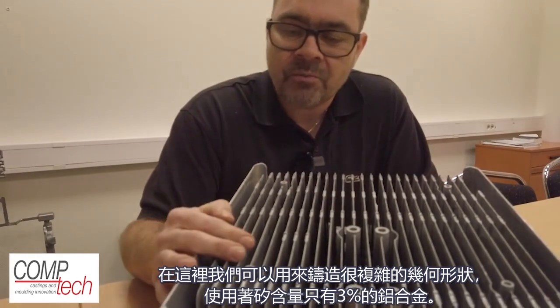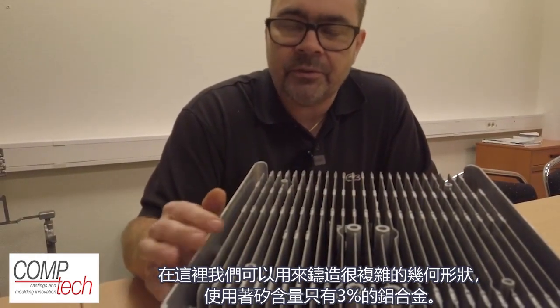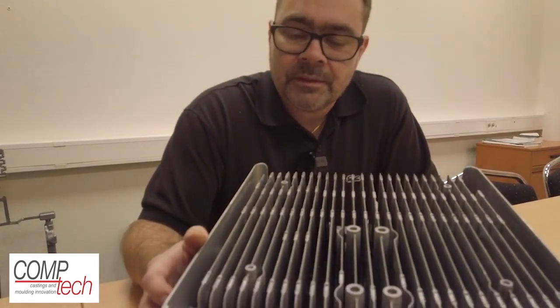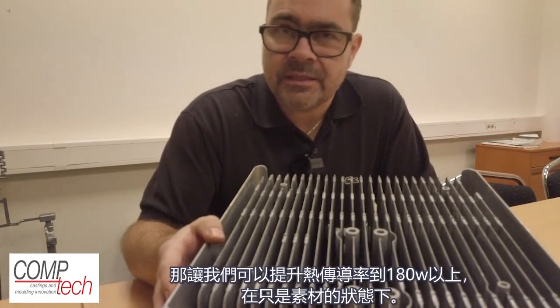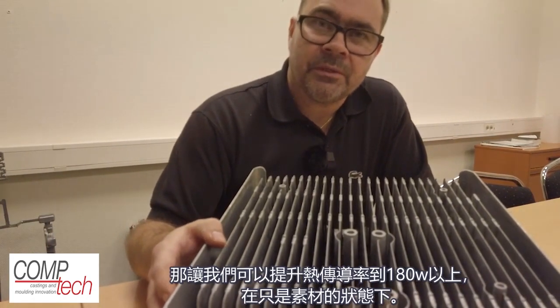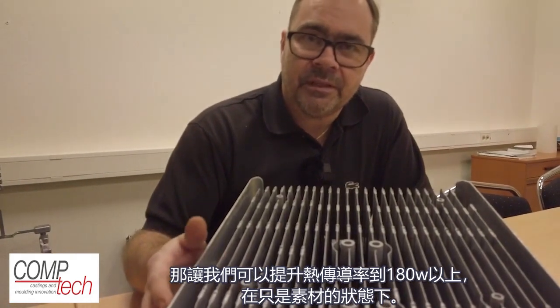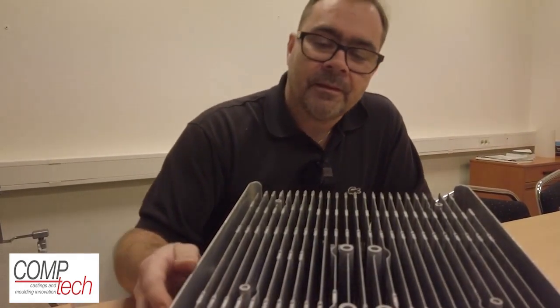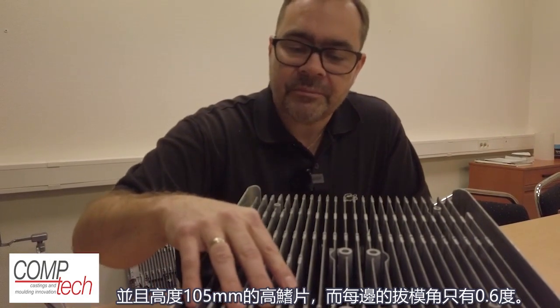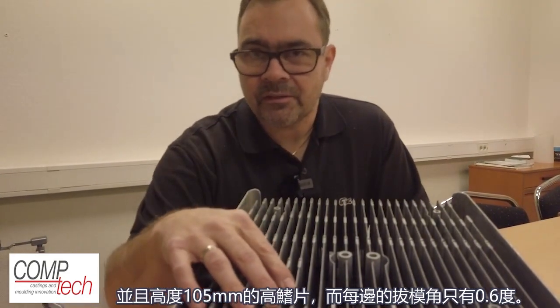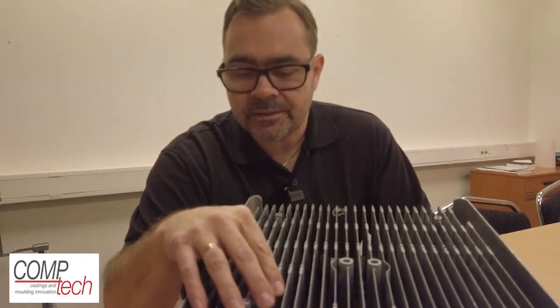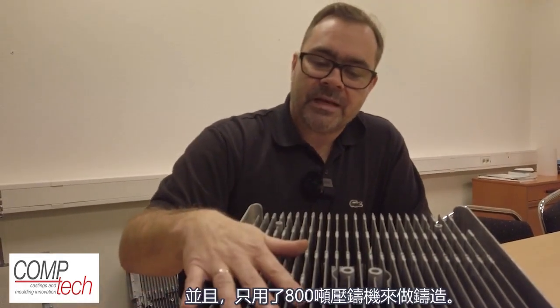Another application where Rheocasting have proven its abilities is within heat sinks. Here we are able to cast very complex geometries in an alloy with only 3% silicon. That allows us to enhance the heat conductivity up to 180 watts per meter Kelvin in as cast state. And 105 millimeter high fins with a draft angle of 0.6 degrees per side, also casted in an 800-ton machine.